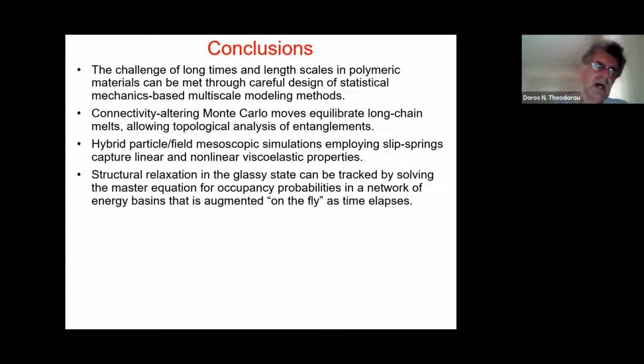The glasses are a great challenge for simulation. We use this idea that a glass is configurationally arrested in the vicinity of a minimum within a basin. So a quenched average over minima can give us volumetric and elastic constants. If we want to look at the relaxation of a glass, how its properties change with time, this landscape picture of the system going from minimum to minimum across a saddle point in multidimensional configuration space